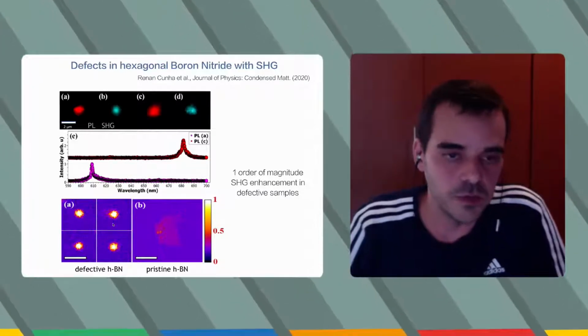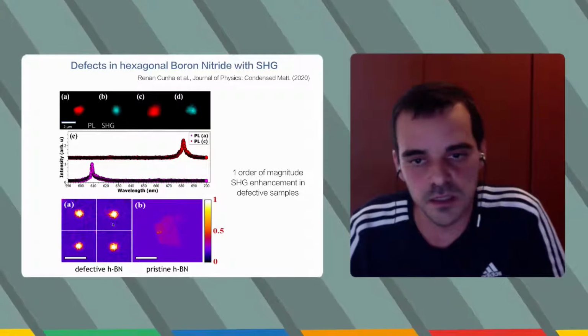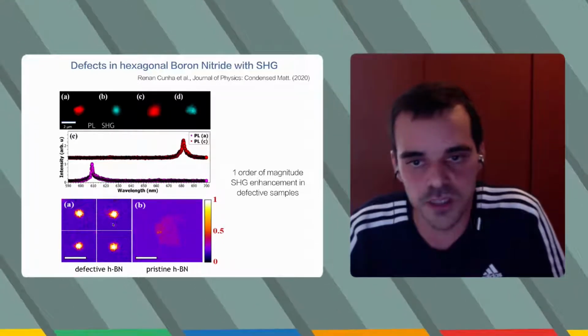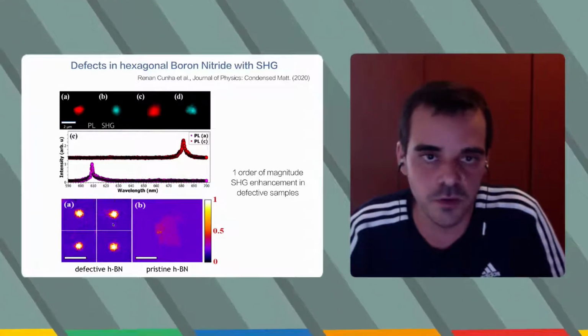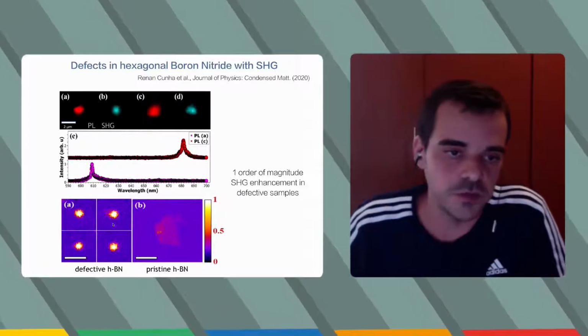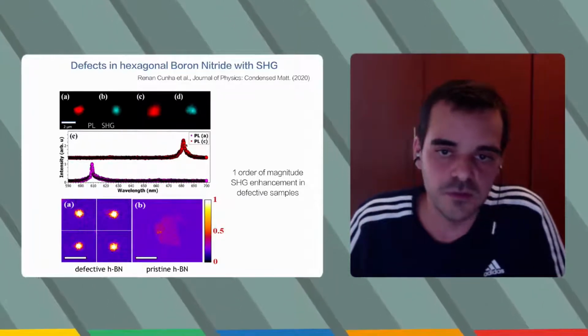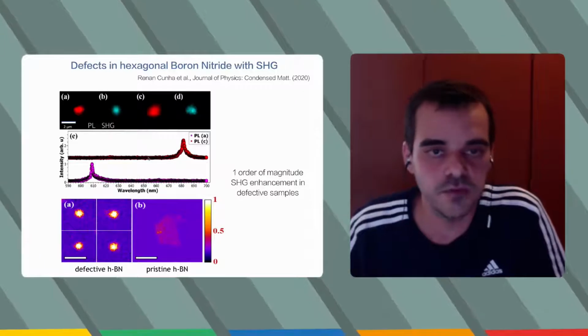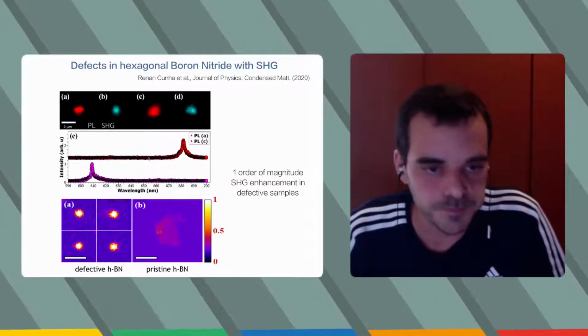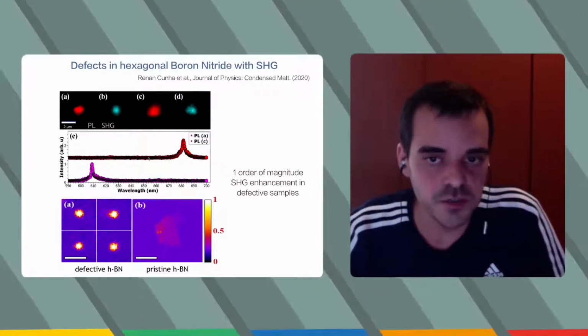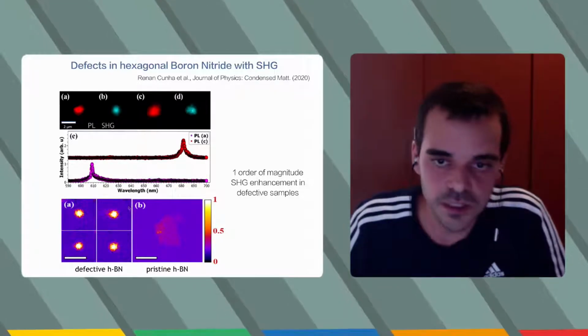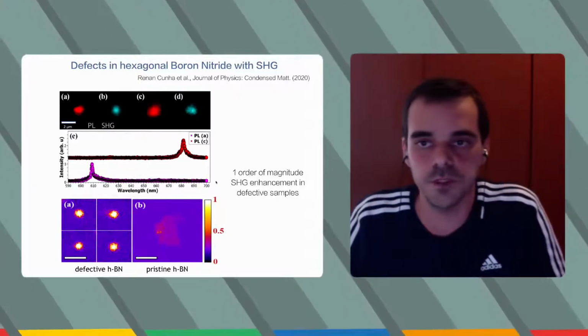It can be that the second harmonic is in resonance with the defect state in the boron nitride. So we try to compare with the photoluminescence from these defects. We have some tentative explanations, but we don't have a complete answer for this.